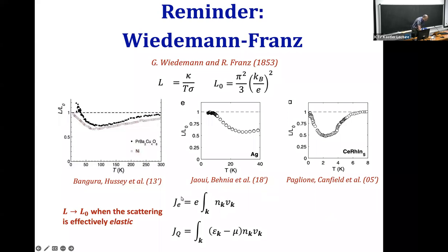It can only modify the velocity. And you see that to relax the electrical or the thermal current, you have to relax v of k. You cannot relax the energy. And therefore, it's exactly the same scattering processes that contribute in the same way to both electrical and thermal resistivity. And this is actually the origin of this law. So the explanation of this behavior of the Lorenz ratio is that at the lowest temperatures, the scattering is elastic. It's dominated by impurity scattering. Then at higher temperatures, phonons kick in and they cause inelastic scattering. This is why it deviates down.